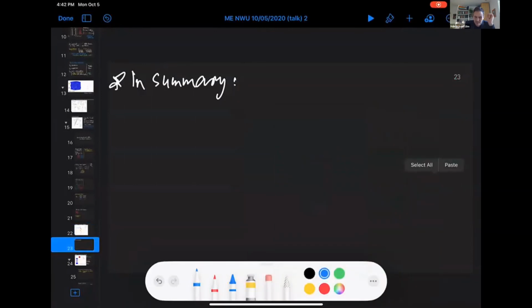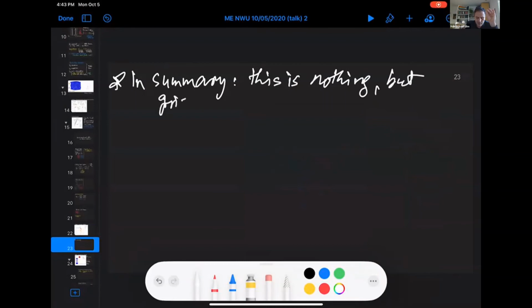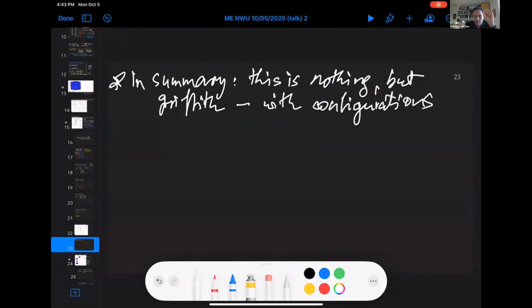In summary, this is nothing else. So keep this in mind. This is nothing else but Griffith, right? Just at the scale of, in a discrete form, in terms of bonds. This is nothing but Griffith, equilibrium based, etc. With one subtle difference, which is that we consider the configurations, these microstates of fracture, as I showed you from simulations. So, which means nothing else but that we're having here the bond